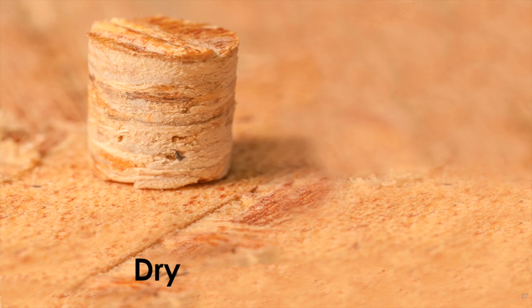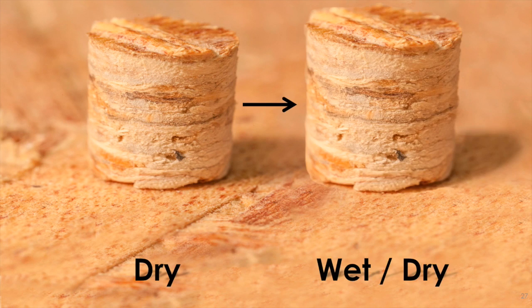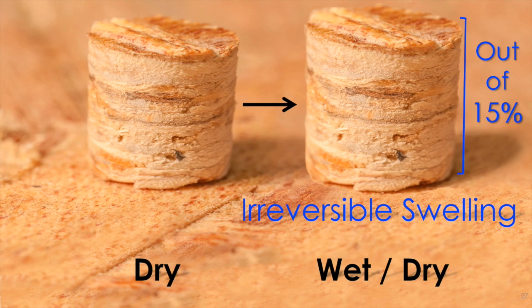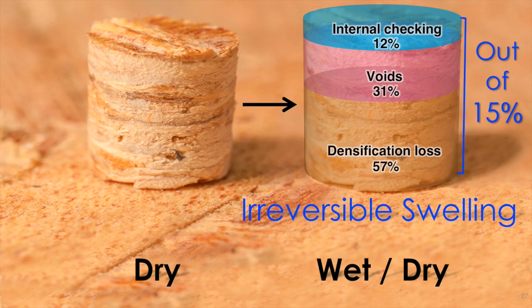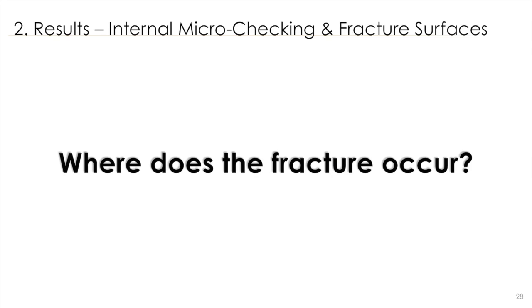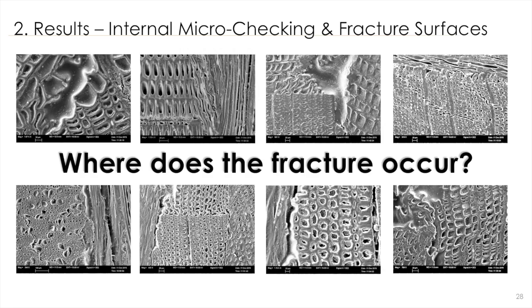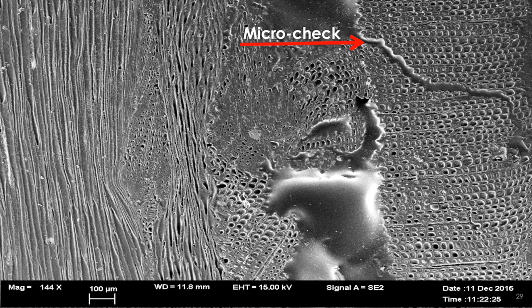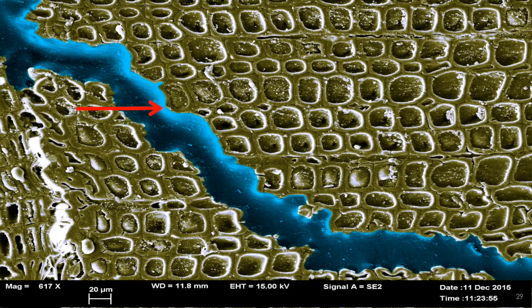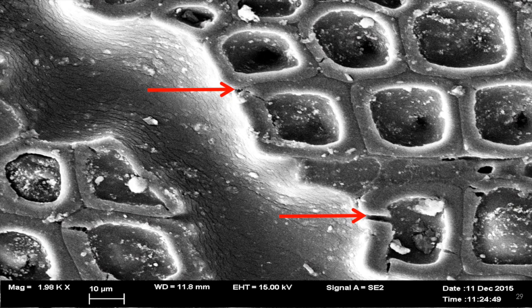And if we look at how that affects changing dimensions, out of 15% irreversible swelling, 12% is taken by internal checking. So finally, where is the fracture occurring? With the field emission FE-SEM images, we sought to find that out. So as you can see from this cross-section of softwood, it's mainly occurring as radial delamination by interwall fractures at the interface between the wood cells called middle lamella, which is lignin-rich, and also in the form of transwall fractures.